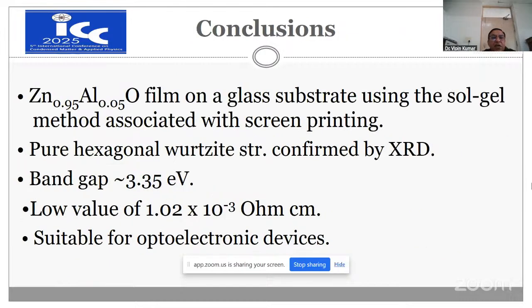Conclusions: Zn 0.95 Al 0.05 O film on glass substrate was prepared using the sol-gel method associated with screen printing. Pure hexagonal wurtzite structure confirmed by XRD. Band gap through the optical results found to be 3.35 electron volt. Low value of resistivity, 1.02 × 10⁻³ ohm-centimeter. Suitable for optoelectronic devices.